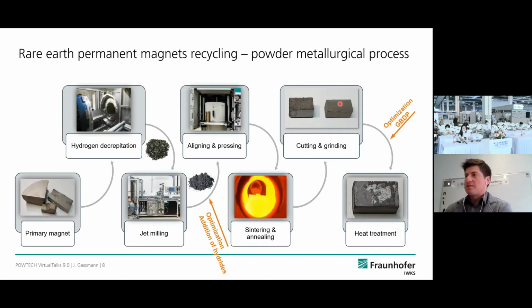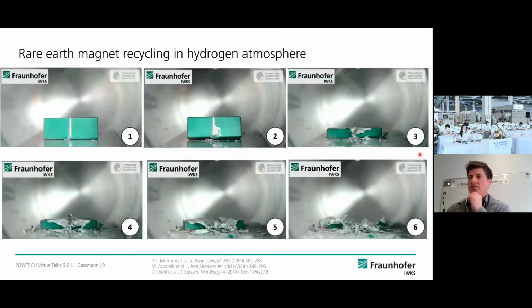So then one ends up with magnets. After a surface treatment and cutting and grinding processes, it can also be coated, but it can also be further optimized by different kinds of processes to further increase magnetic properties. So here the process is shown for hydrogen decrepitation, as it was developed already in the early 1980s in the UK. Basically, the magnet is shown in a hydrogen atmosphere after different times. One can see the hydrogen diffusing into the magnet. Stress is occurring, which powderizes the material. And this powder can be directly used for producing recycled magnets.